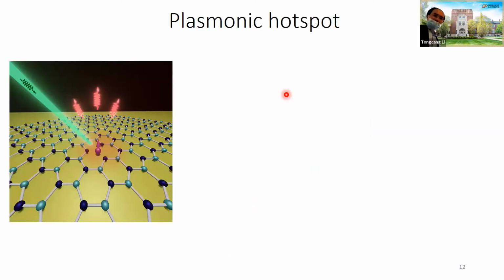And now with this spin defect, great, we want to enhance the brightness. One way to do it is to use plasmonic enhancement. Because we also want to use this for sensing, we want to use the simplest geometry possible. The simpler, the better. So the simple one is to directly put the hBN flake on gold film.